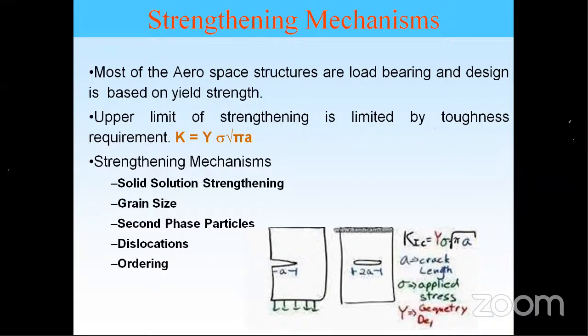So we have an equation, K = Yσ√(πa). As you can see, a is the half crack size, and K1C is equal to this. So based on this, in presence of a crack, we can find out the available strength of this material using the fracture toughness value. K1C is also a material property.